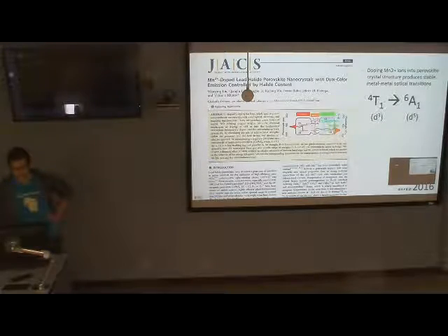Yeah, so the idea is that non-radiative relaxation from this manganese state to this band edge is going to be quicker than this emission process, which is on the order of, I think, milliseconds. So non-radiative relaxation is generally faster than millisecond. And that's been shown in other systems too, where once you get to red emission of your intrinsic dot, you don't see emission from the manganese anymore, which I think I have a paper on in here too, which we can get to eventually.